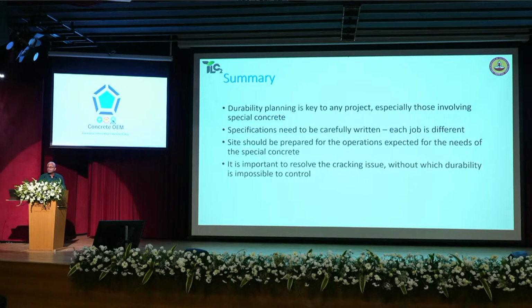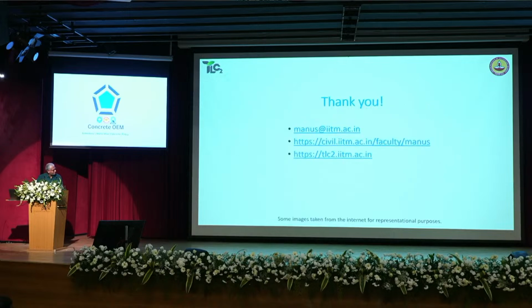Again, for durability, we know that we use special concretes of low water cement ratio, high supplementary cementitious materials dosage, higher strengths, and so on. But what's the point of having durability when you have cracks, right? Water or chemicals will not find their way through the concrete. They'll go right through the crack. Why do they have to worry about trying to penetrate through dense, impermeable concrete? You need to have crack-free concrete. Only then can you actually execute projects which can last for a very long time. Right, thank you all very much.